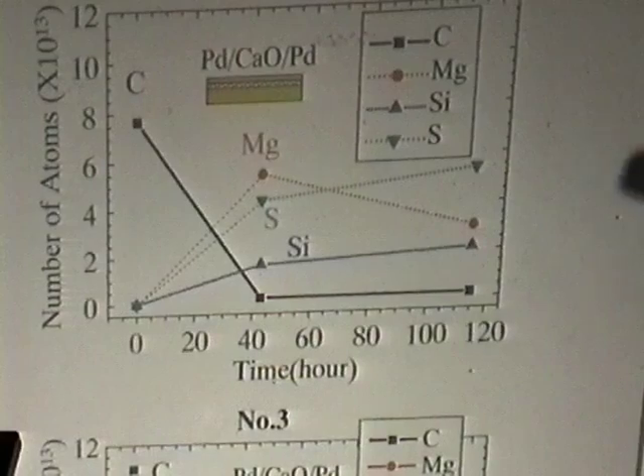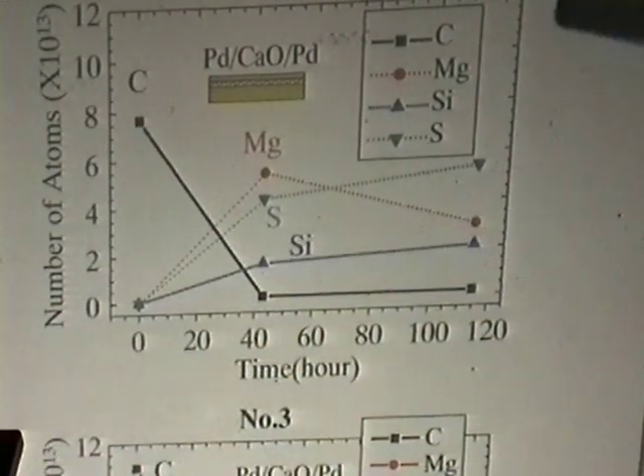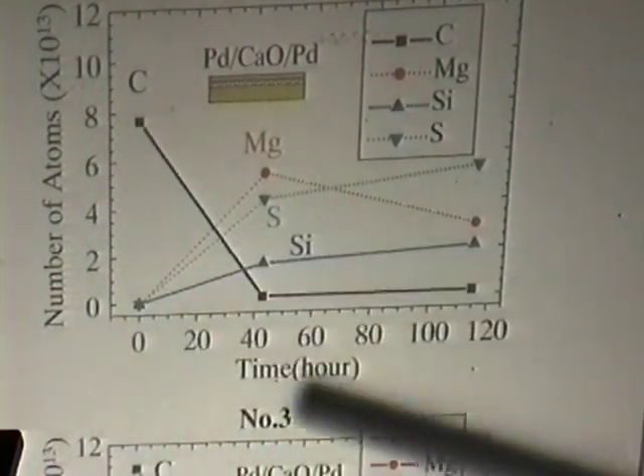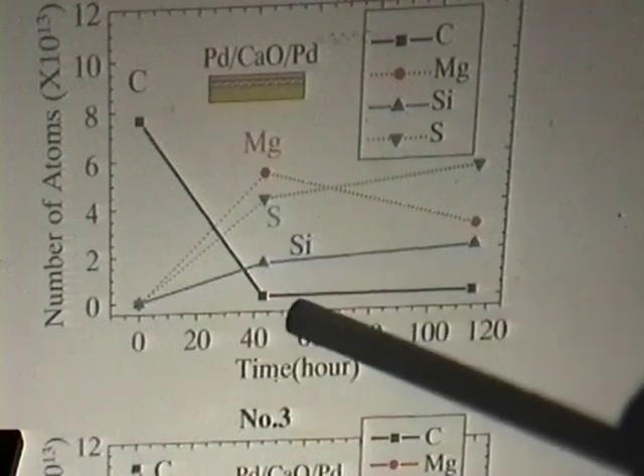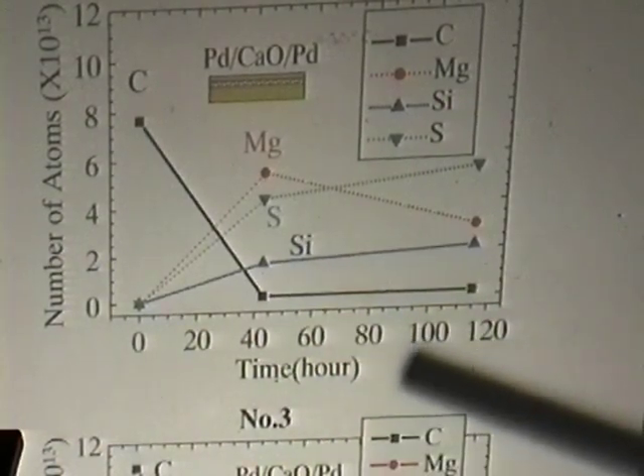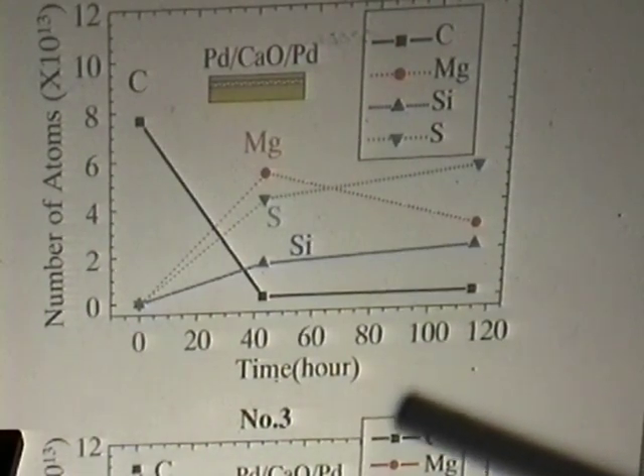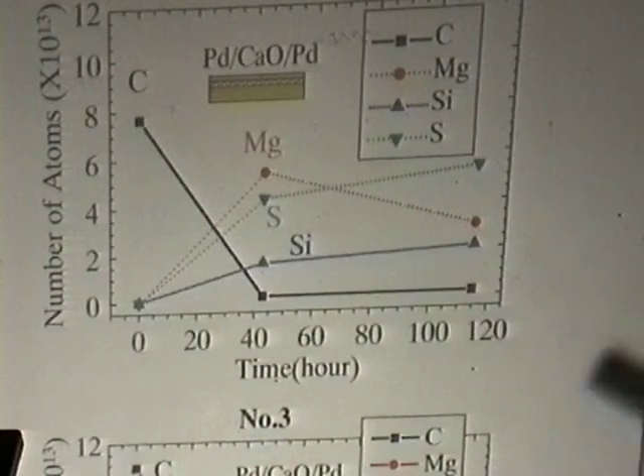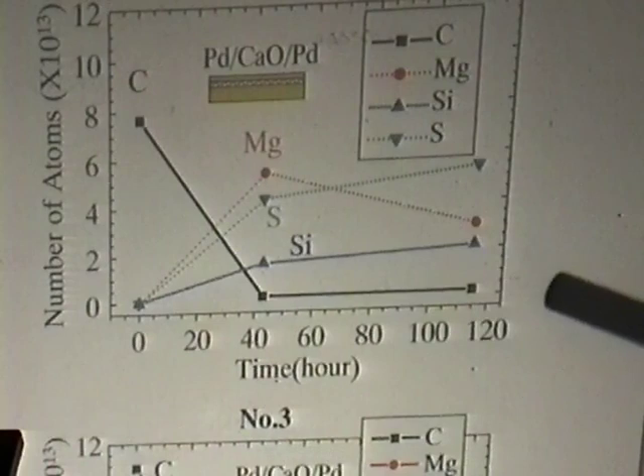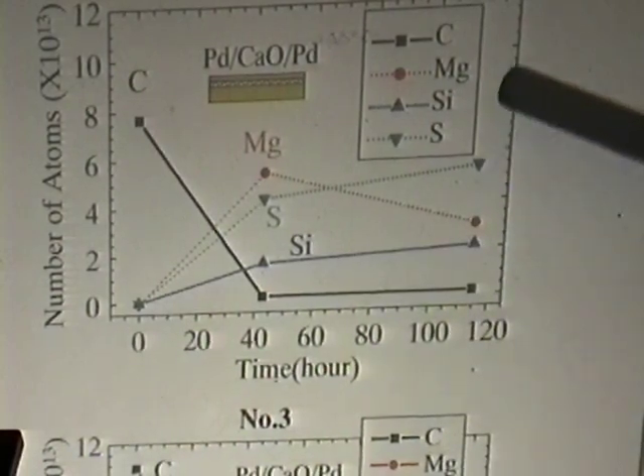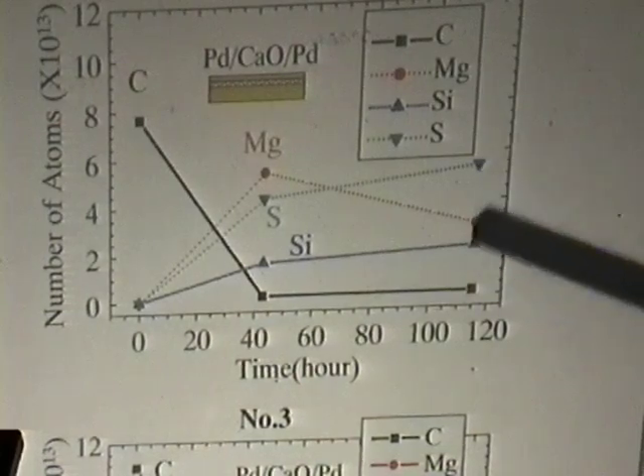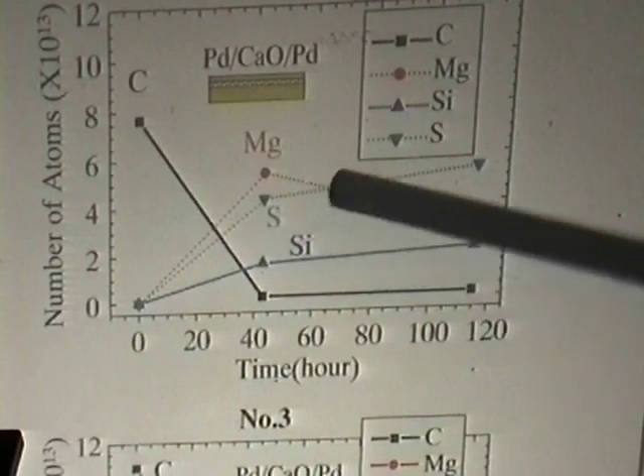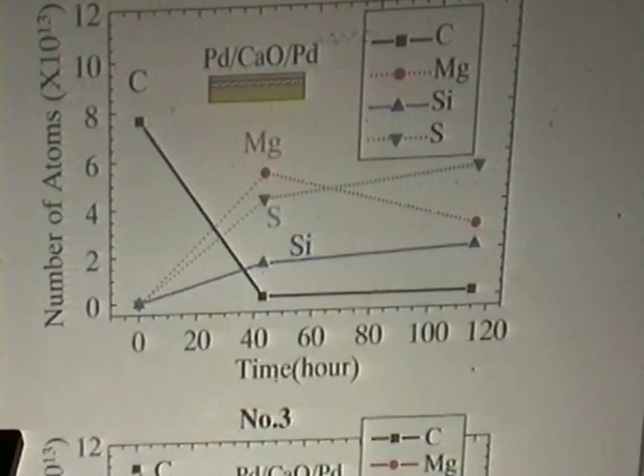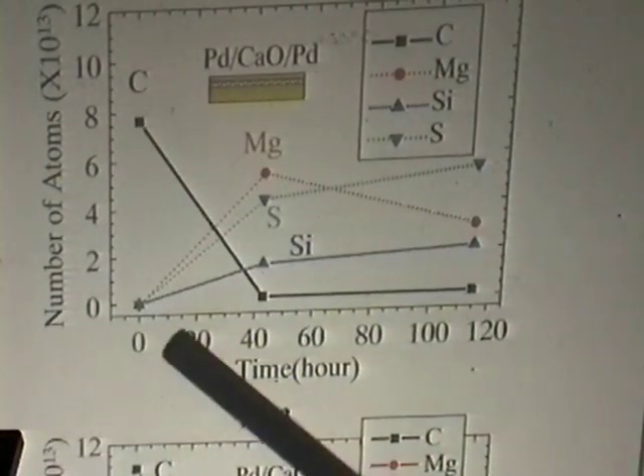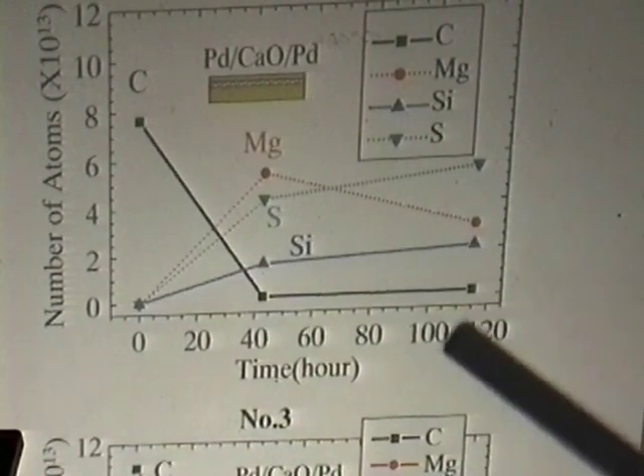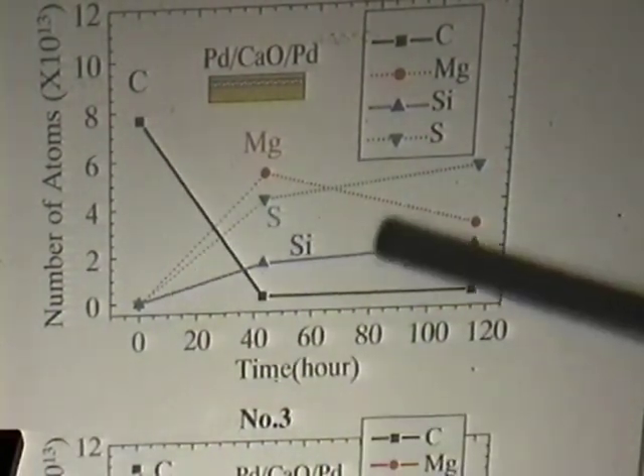But after 42 hours, we obtain magnesium, sulfur, and silicon XPS peaks. On the contrary, the carbon peak was reduced. At the time equal to 116 hours, sulfur and silicon increased and magnesium decreased slightly. Carbon decreased. Silicon and sulfur increased monotonously, and magnesium once increased and then decreased.